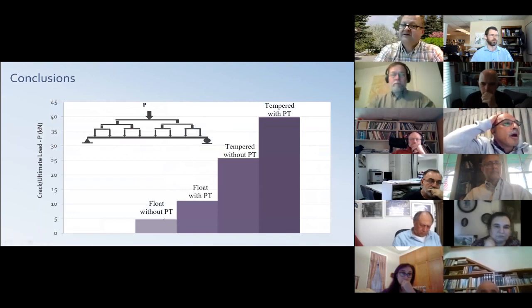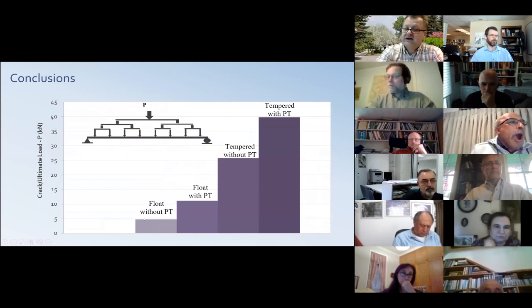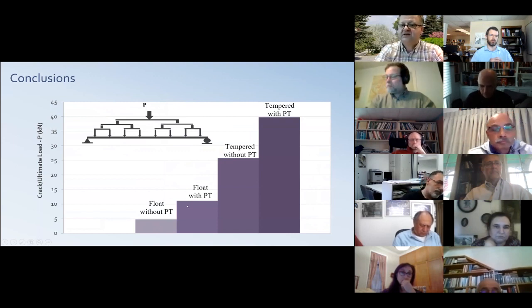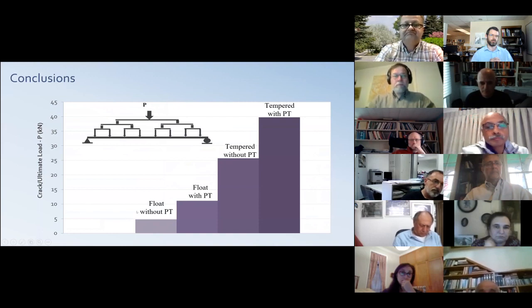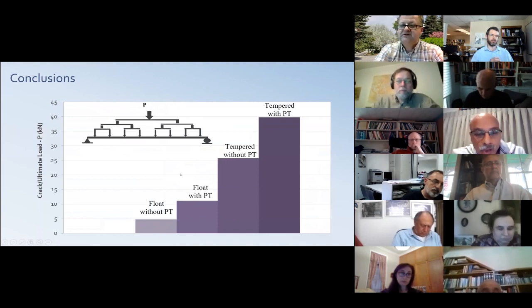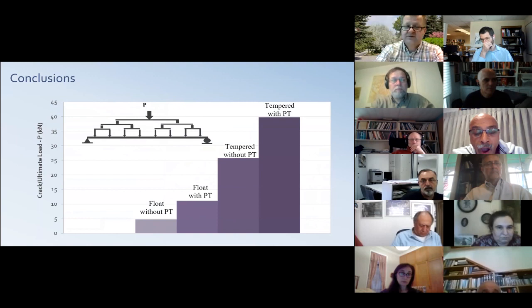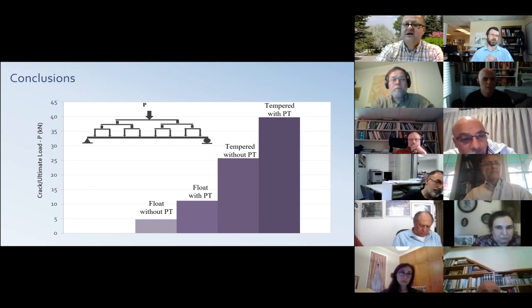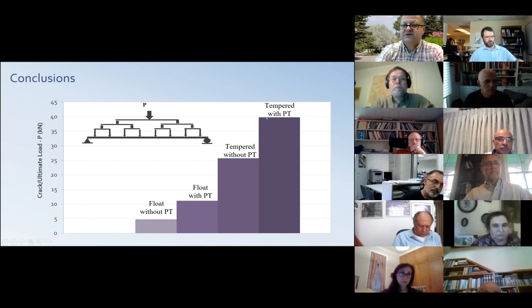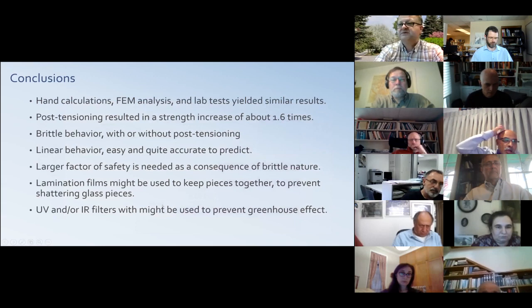When we compare the float glass without post-tensioning, it had the smallest strength. And when we apply the post-tensioning, we have improved the strength by more than 2 times. This is tempered glass without post-tensioning. So when you compare this with the regular glass, you see about 4 times strength increase. This is meaningful because about 30, 40 megapascal versus 120, 160 megapascal, the tensile strength is about 4 times. And then when you apply the post-tensioning to the tempered glass beam, we had a superior strength to all the other beams.